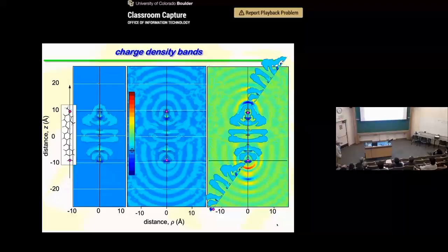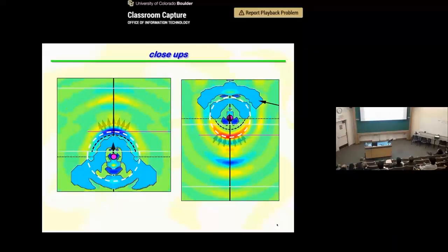This shows these bands matching the bands of the molecule. So this is the region around the end, the tethering point. So this is a fixed nitroxy, the 2 oxygens, and the methoxy groups of the tethered molecules rolling around, sliding around. This is the van der Waals surface, sliding around, strongly attached to this nitro. And then here's the other end of the molecule where you have the methoxys, occupying a large volume because they're so flexible, and then the nitros attaching. So this attachment's like 2 magnetic ball bearings rolling around on each other.